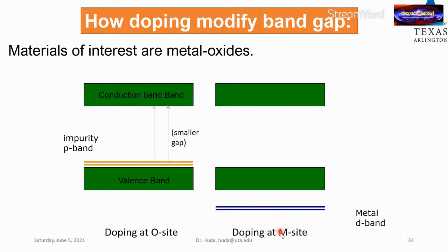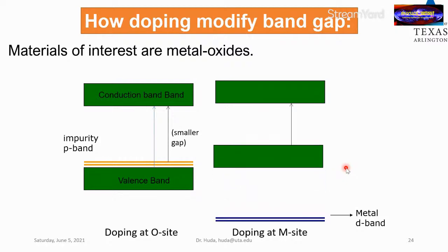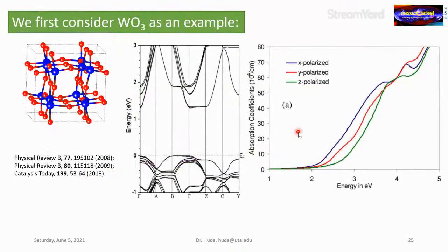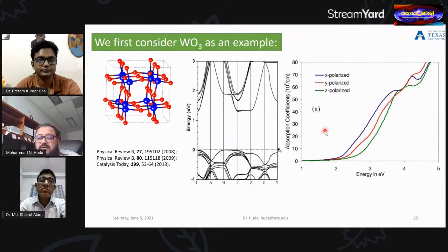Now, of course, we can dope on the metal side for the metal oxide. If we do that, doping at the metal side, the metal d band, if we consider transition metal, those d bands usually sit below the valence band, somewhere within the valence band, basically. And then once the metal d band sets in there, there is a hybridization of the oxygen p and the impurity metal d. This hybridization will basically push the valence band up. The hybridization is splitting, bonding, anti-bonding is splitting. Because of this splitting, the band gap can also get reduced. These are the 2 simplest mechanisms that I can show for how we tune the gap, we reduce the gap by doping.